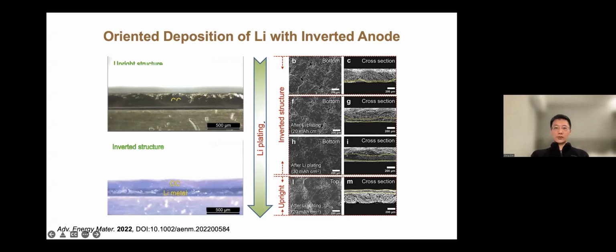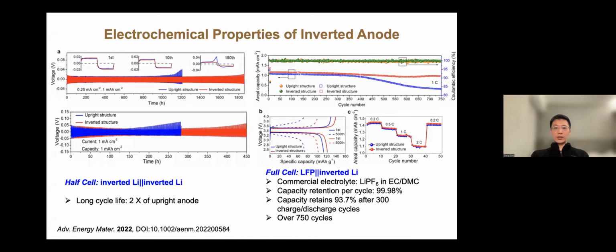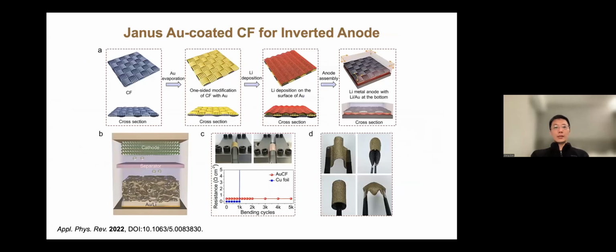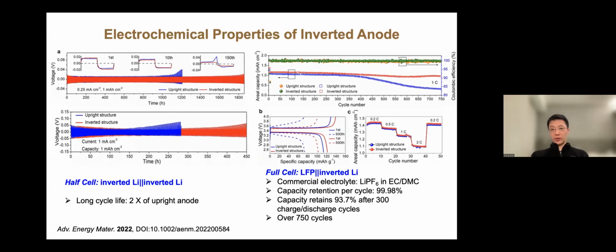So I think this makes a nice example, and then we use that to run a cell in a very long cycle. This is 750 cycles of lithium metal running, and it was quite successful in EC/DMC, a commercial electrolyte, with a capacity retention of about 99.98%. Now we can make it flexible, whereas the previous one is not flexible.